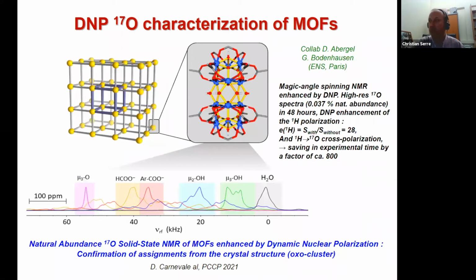This structure, we of course used additional techniques to confirm it. So we tried two techniques in our lab. One of them was pair distribution function analysis, but it was a little bit puzzling because the signature of a Zr6 and a Zr12 cluster is almost the same. If you look at the Zr12 cluster, it is basically two Zr6 clusters that are connected by mu2-OH groups. So it does not give rise to significantly different PDF signatures.